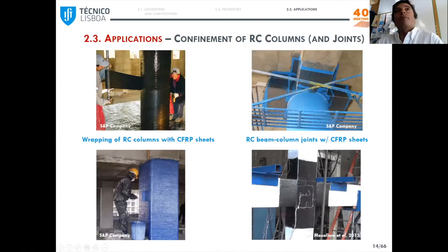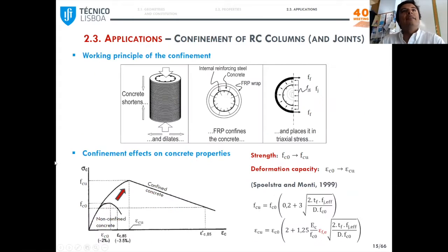Here I show some common applications of CFRP sheets in wrapping columns and also beam-to-column joints where they provide confinement. And here I try to summarize the principle of this confinement effect. So when concrete is compressed in the axial direction, due to Poisson effect, it tends to expand in the transverse direction. And here the FRP wrap will prevent such lateral dilation, promoting a triaxial stress state. And so the practical consequence is that both the compressive strength and the ultimate strain of confined concrete will increase very significantly compared to normal concrete.